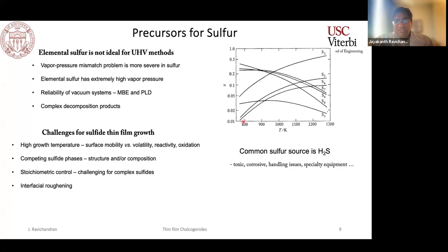But as you change the temperature at which you are trying to crack your sulfur, the relative ratios of various different types of molecules that you can get changes dramatically. And this also tries to push your sulfur equilibrium back and forth depending on what sort of conditions you're working with. And this leads to very poor incorporation of sulfur. The controllability is fairly bad.